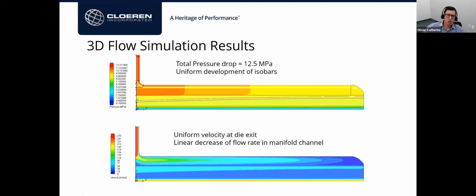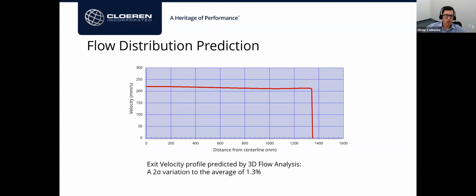Here's the result. So we have a pressure drop of 12.5 megapascal, which is very nice, and a very uniform velocity at the die lips, computed from commercial 3D computational fluid dynamics. Same results showing here, a plot of the velocity distribution at the die lips. And you can see, compared to the theoretical design, we have a flow variation of 1.3%, which is basically nothing.